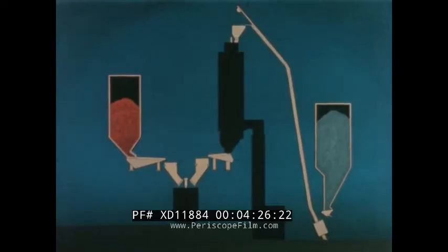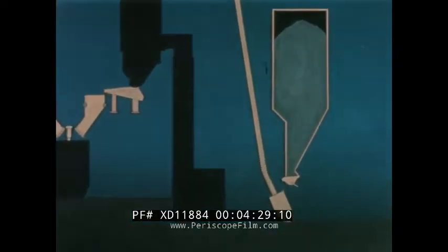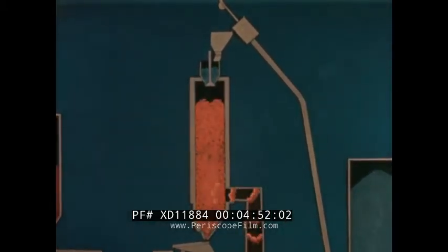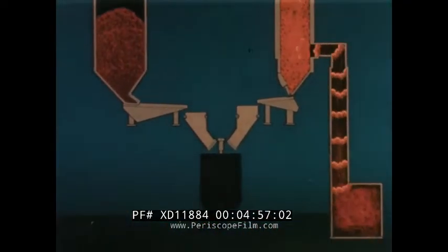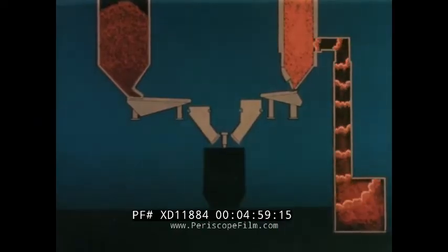Smelting takes place in a blast furnace, which requires controlled supplies of lump sinter and metallurgical coke. The coke must be preheated to 800 degrees centigrade. In readiness for this, the coke is first fed to the coke preheater by a skip hoist. Blast furnace gas produced in the process is used for preheating the coke, being burned under carefully controlled conditions and in contact with the coke.